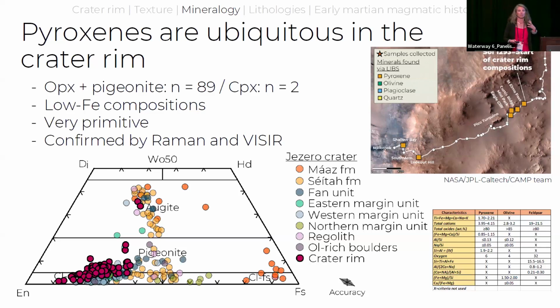So what's really cool with them is that most of them are actually low calcium pyroxene. So you can look at this pyroxene quadrilateral: on the left you have magnesium, on the right you have iron, on the top you have calcium. All the purple-red points represent the crater rim pyroxene, and you can see that they're all low calcium pyroxene. 89 of them are actually OPX and pigeonite, and we have two sad little CPX up there. So they have, as you can see, low iron composition, high magnesium composition, which differs a lot from, for example, pyroxene that we found in the crater floor.